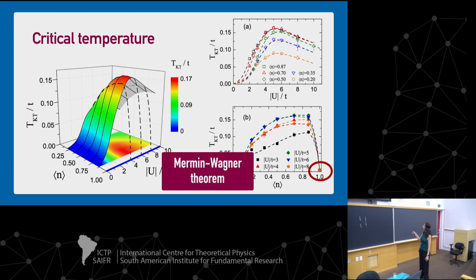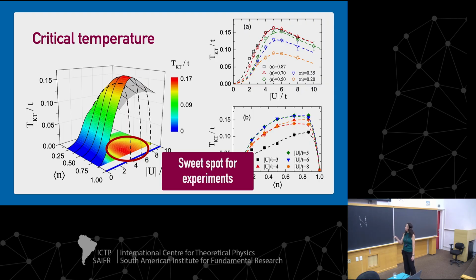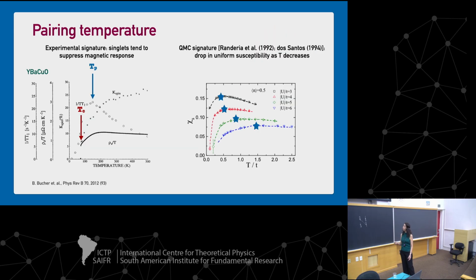Once again, we have to have TC going to 0 at half filling because of the Mermin-Wagner theorem. But he found this, which I find very useful for experiments, this sweet spot for experiments, the region where the Kosterlitz-Thouless transition is, the temperature is higher. So around 5.4 U, and the density around 0.8, 0.7. So you know where to look when you want to find a higher temperature.